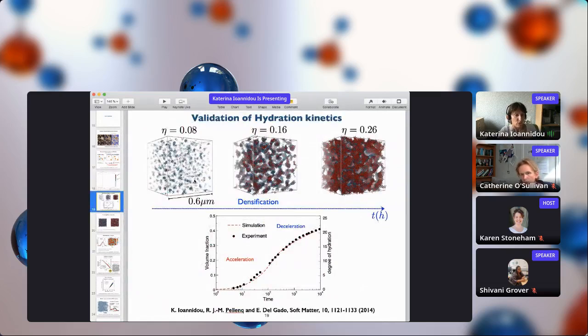If we want to see a bit more, the phases we go through are shown here. We start with the cluster phase, then an accelerated precipitation, the formation of a gel, and a decelerated phase where we have the densification of this gel and the creation of the porous solid.